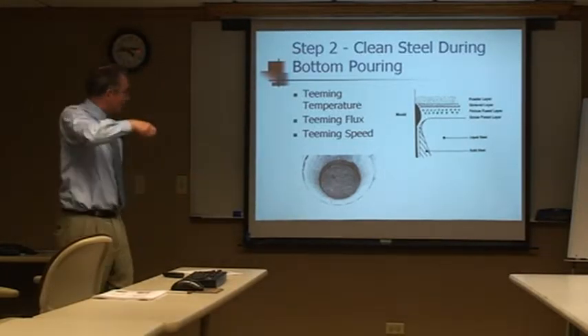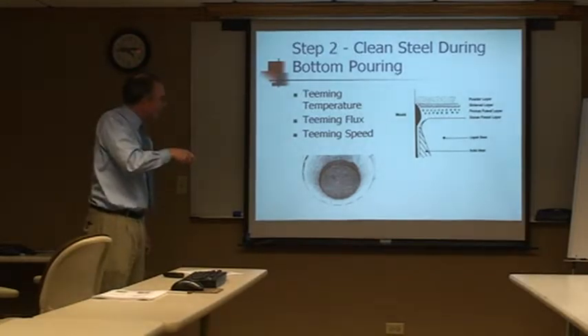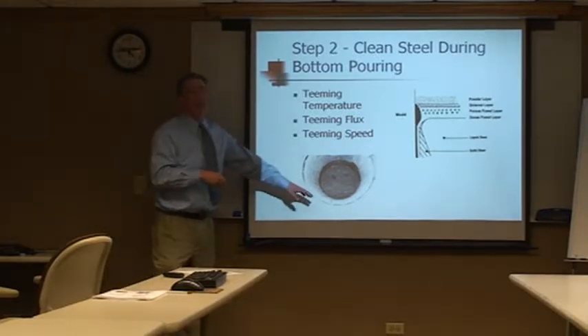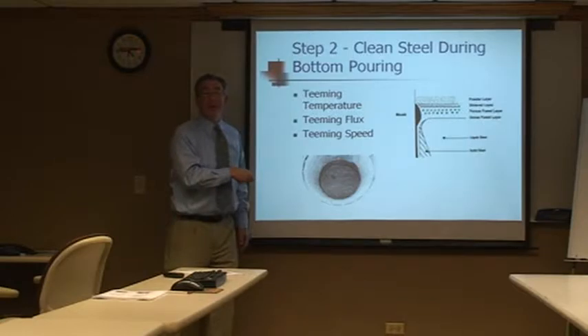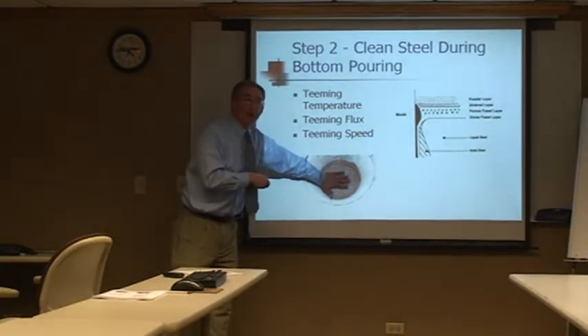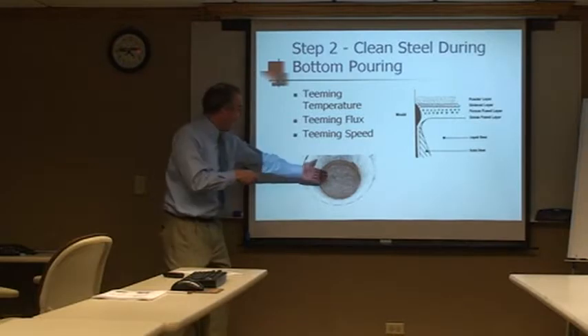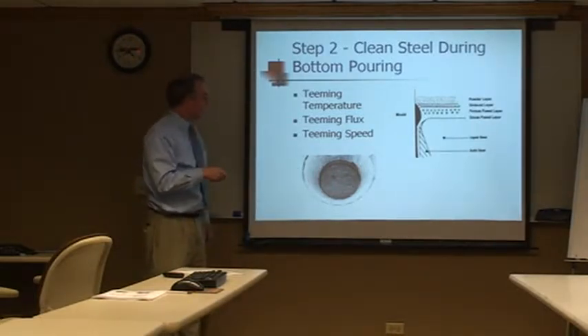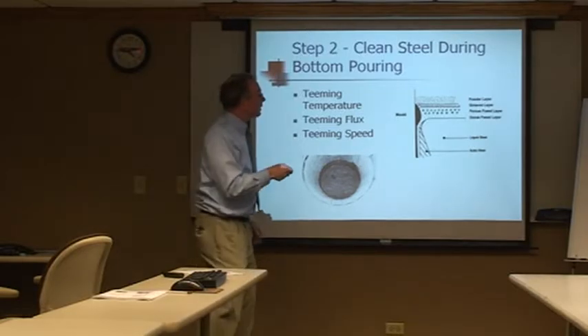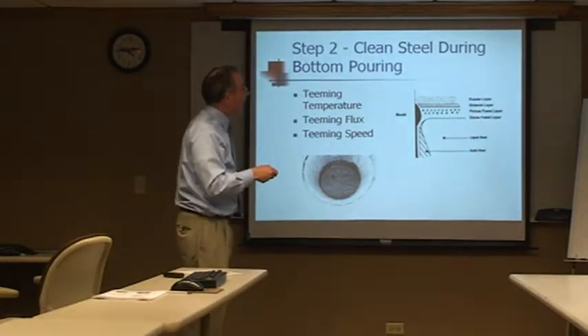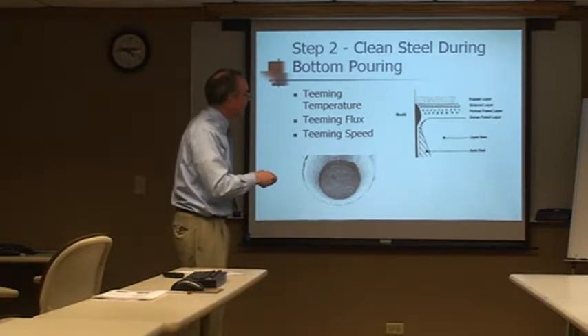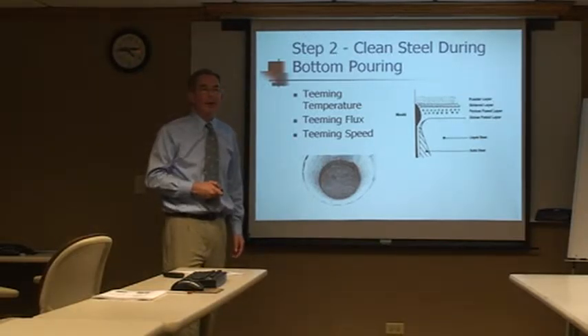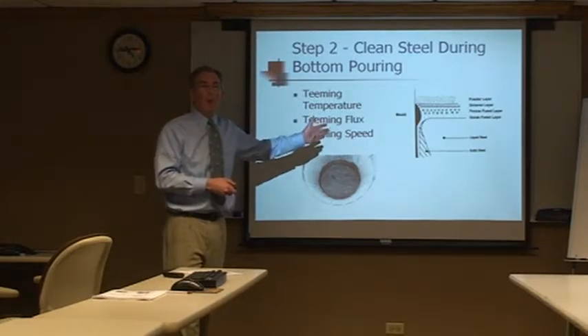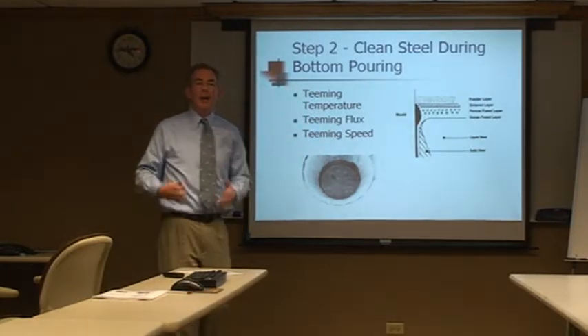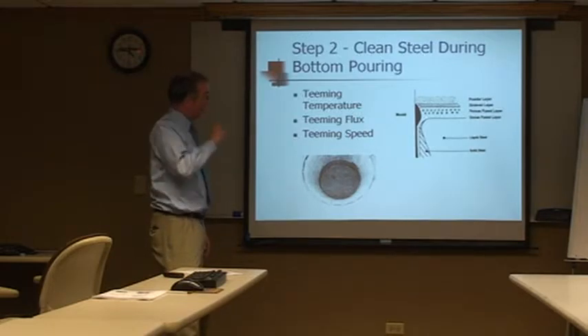So if you can imagine, we're looking down in the mold here. Can you see this surface right here? That's the steel right there. But it's black and white, so trust me, it's not orange, it's black, because that powder is completely covering the mold as it's rising up. So we're not exposing the steel. The other thing that this flux is doing is that this glassy lubricant is also feeding down alongside the mold wall here, acting as a lubricant, so that the steel doesn't stick to the mold wall. And we end up getting a very good ingot surface quality as a result.